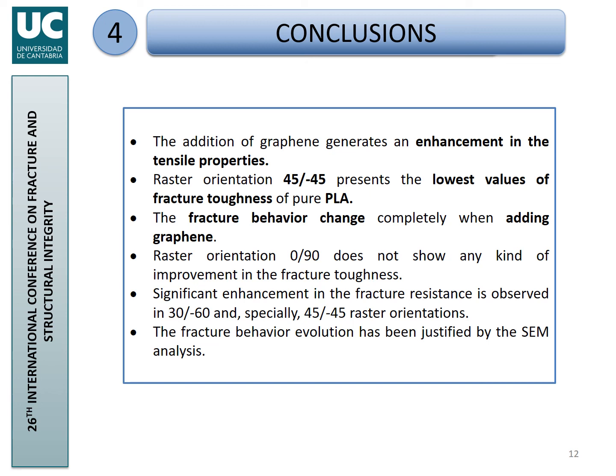Raster orientation 0/90 does not show any kind of improvement in fracture toughness, and on the contrary, the fracture resistance shows a clear increase in the 30/-60 and especially 45/-45 raster orientations. And all these observations have been justified by the evolution of the fracture micromechanisms observed in the scanning electron microscope.